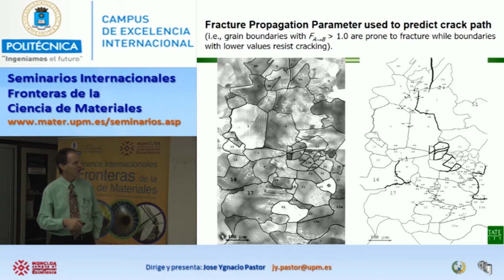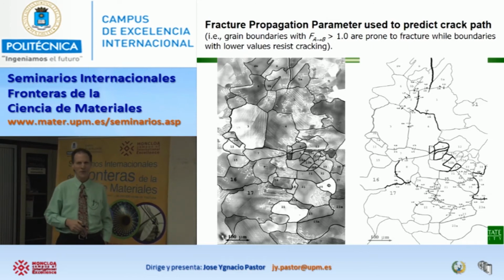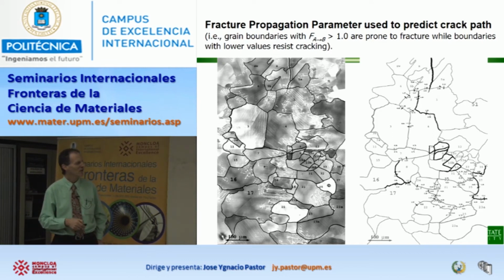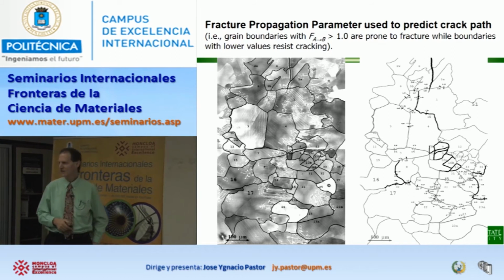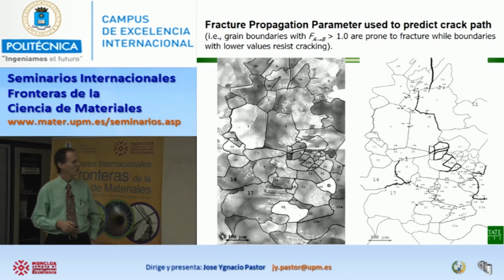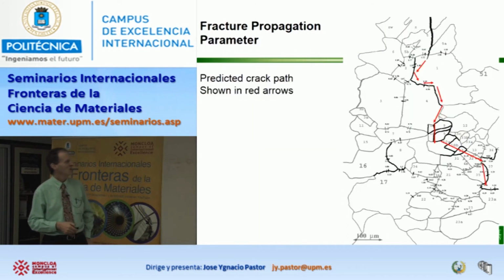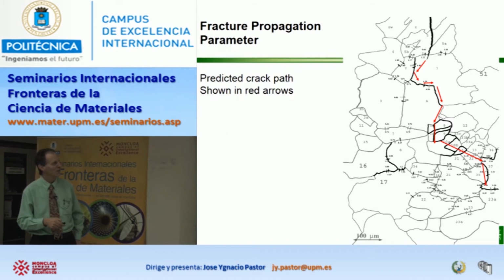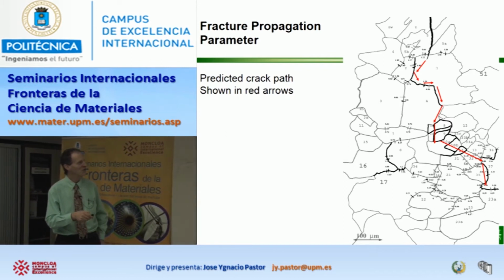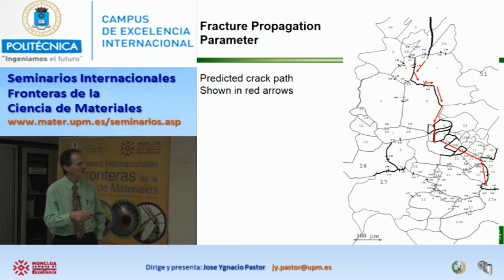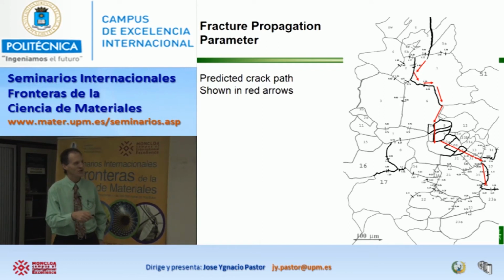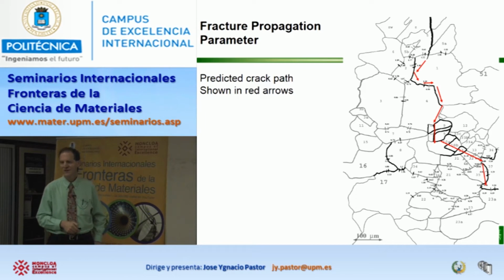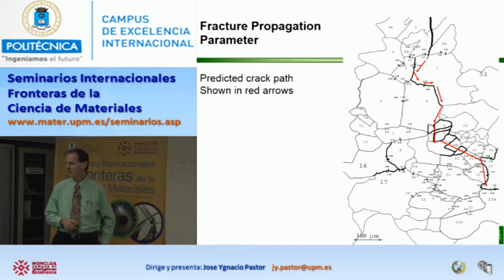Well, here's a map showing all the grain boundaries. And then if we use this fracture propagation parameter, we can outline the boundaries that have higher values. And then the ones that are not dark don't have as high a value. So they would be more resistant to cracking. So the question is, well, could we? This seems like a possible prediction direction. But that's kind of strange, because if we just follow what these numbers say, the crack seems to be headed for this region where all those microcracks are. But then this suggests that it's going to make a right angle turn and go away in a different direction. So that was interesting, what would really happen.